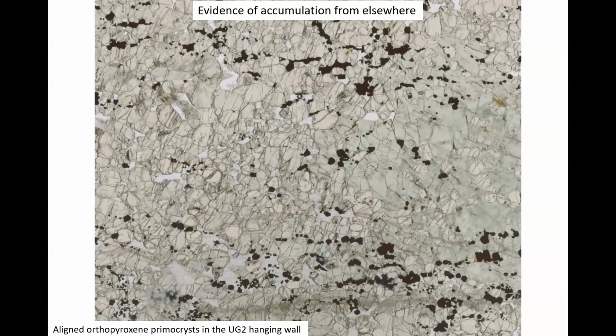John Lundy mentioned the fact that if you're dissolving a crystal, you make it round. The signature for Ostwald ripening is that the grains below the critical radius, the ones that are dissolving, are rounded, and the ones that are actively growing are faceted. So you would look at the shape of your crystals as a function of size in your different oikocrysts and see if you could pick out the point at which ripening started to be important. That would be a really nice thing to do. You can also come to the poster session, where there's a very nice example of that.